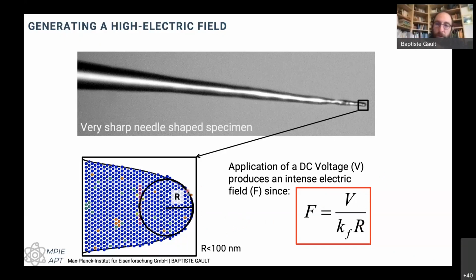So what we are actually doing is not exactly taking a sphere and suspending it in vacuum, right? We just take a very, very sharp needle, as I've shown you from the TEM image before. And near the apex of the needle, we have a surface that is highly curved, which is more or less like a sphere. If we apply a voltage of a few kilovolts and the radius here is in the range of tens of nanometers, if we divide one by the other, we get to the right range of about 10 to the 10 volts per meter. Because this is not a sphere, we have a geometrical parameter here, which we sometimes call the field factor or field reduction factor, which is somewhere between 3 and 10, depending on the specimen geometry and the microscope geometry. But basically, with just a few kilovolts and a sharp tip, I can get to the fields I need to start removing atoms from the surface of that specimen.